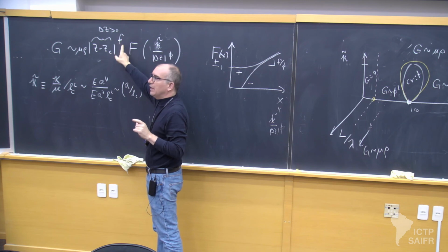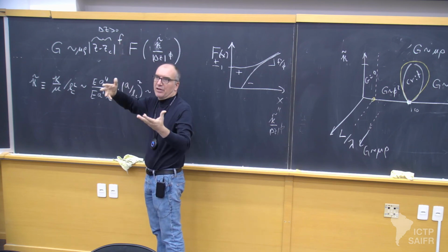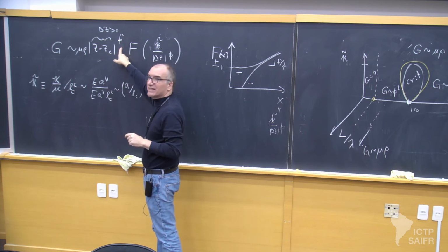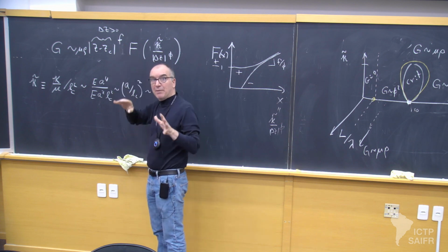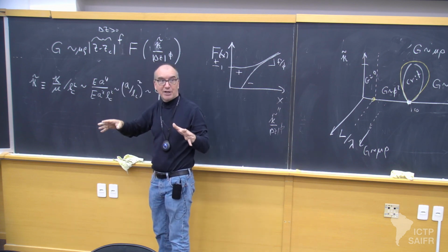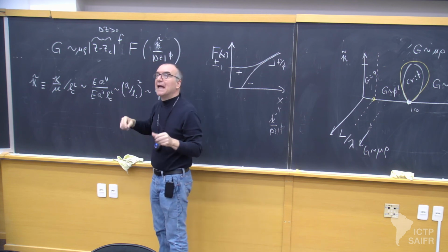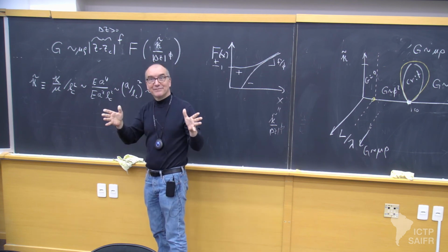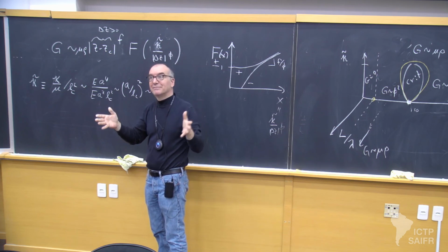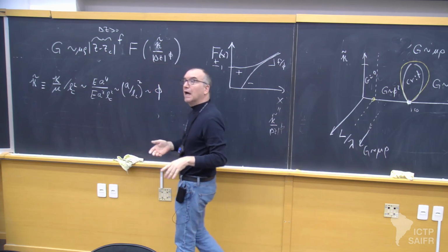And in 3D, slightly bigger error bars because it's harder to do big systems in 3D, it's 1.6. So interestingly, it's non-mean field even in 3. That has implications for the upper critical dimension for phase transition fans. Unlike jamming being mean field by all accounts. These are different.